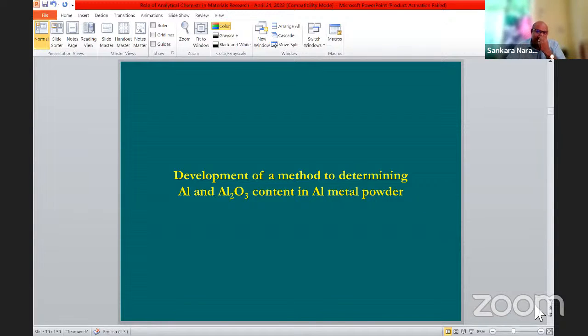So what we did is, myself and my colleague, we developed a very simple method. Metal powders generally react spontaneously with acid. You put hydrochloric acid, particularly, aluminum will immediately react and a lot of hydrogen evolution will become a side reaction, because metal dissolution is the anodic reaction and hydrogen evolution will be the cathodic reaction. So a lot of hydrogen evolution is coming. So we thought, we want to use a simple gas evolution apparatus. You might have seen a gas evolution apparatus.